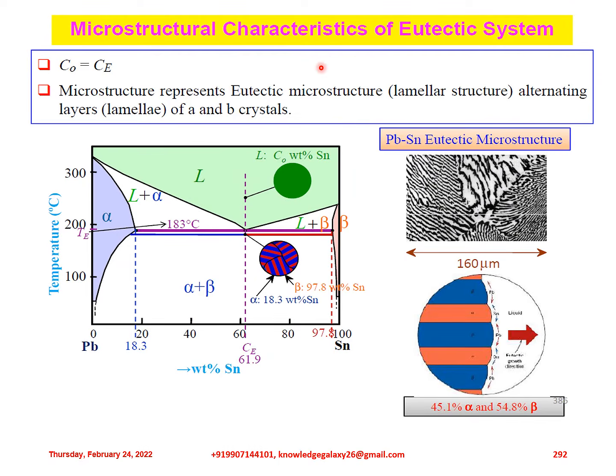I hope we are going so far so good. Further explaining the microstructural characteristics of the eutectic system. In this second case, C0 is equal to C eutectic, meaning we are considering the eutectic alloy. Here the microstructure is a eutectic microstructure, that is, a lamellar structure with alternating layers, or lamellae, of alpha and beta crystals. This is the eutectic point where the reaction is taking place, which has C equal to 61.9% tin, and LC0 is the weight percent of tin, which is the same as the C eutectic weight percent. The eutectic reaction takes place at 183 degrees Celsius. The different phases present here are mentioned. You can observe this by pausing the video. I have just explained the details of it.